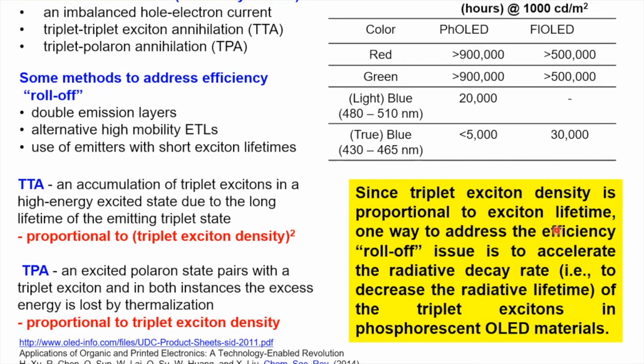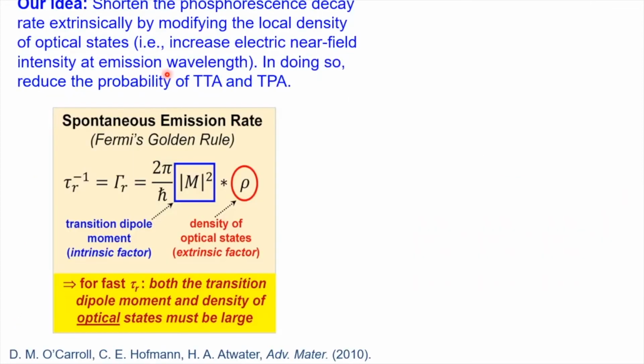So in general then, since the triplet exciton density is proportional to the exciton lifetime, one approach to addressing the efficiency issue is to accelerate the radiative decay rate of the triplet excitons in the phosphorescent material. Our approach to addressing the instability of blue organic phosphors is centered around the use of localized electromagnetic fields of metasurfaces and using them to shorten the phosphorescence decay rate extrinsically by modifying the local density of optical states. And in doing so, that should drive down the probability of triplet-triplet and triplet-polaron annihilation.